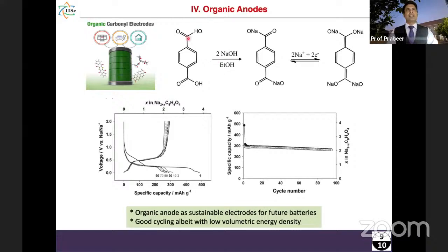So basically this double bond and all this can break, and it can form a single bond here and one bond with sodium. As a result, all the double bonds can break, we can get some sodium based compound, and some more sodium can also go here. So here I can show 0 sodium to 2 sodium to 4 sodium. Basically 4 sodium can go in and out like that. And with this, we can get some nice low voltage operation with capacity around 300, which is very close to hard carbon, and very good cycling stability.